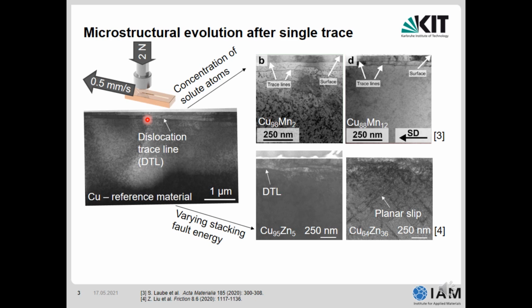In the next step, we have here a brass system, and here the stacking fault energy decreases with increasing zinc content. So here with the lowest zinc content, you can still see a dislocation trace line. So here's also the higher stacking fault energy, and with the lower stacking fault energy, we can see a planar slip.